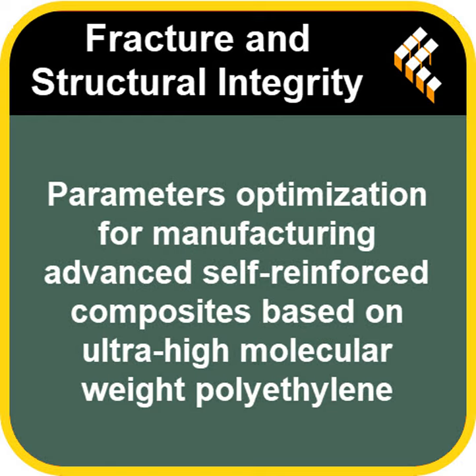It's all about controlling that delicate molecular dance at the interface. Get it right, and the results are amazing. Get it wrong, and they plummet. So summing up the amazing part then, we're looking at UHMWPE self-reinforced composites with, well, exceptional tensile strength, that 1440 MPa figure, capturing maybe up to half the strength of the original fibers. Which is incredible efficiency. Plus, they fail gracefully, right? Not brittle fracture, but that ductile bending and energy absorption. Fiber pullout, plastic deformation. Yeah, really important for impact resistance and avoiding catastrophic failure.